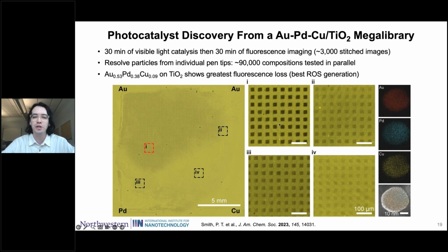So there's larger ROS generation compared to panel 4, where there's only a little bit of loss of fluorescence. And so then we can use this and determine which composition had the highest ROS generation. We discovered this gold 53, palladium 38, copper 9 on titania, which we can then recreate and show that it's this alloyed structure. And so this is our promising discovery for photocatalytic ROS generation.